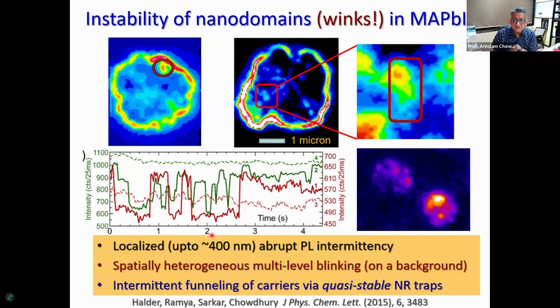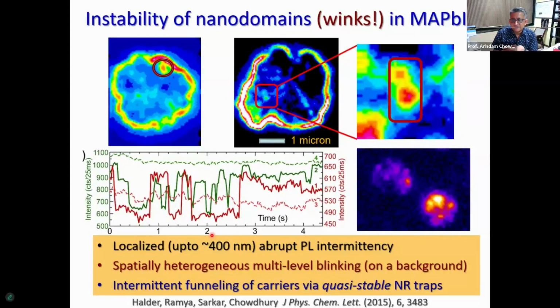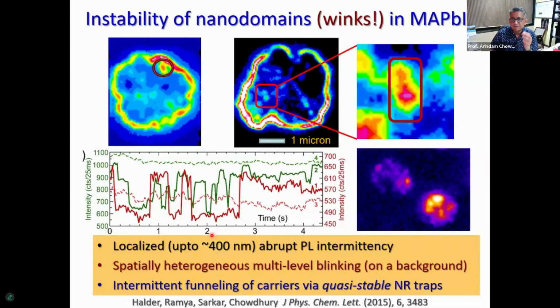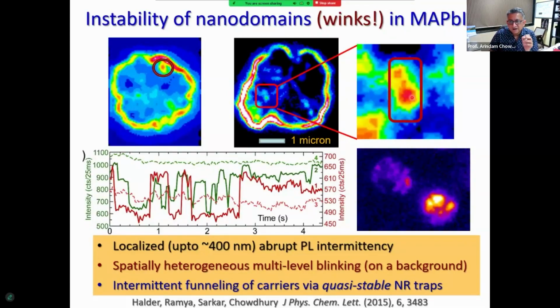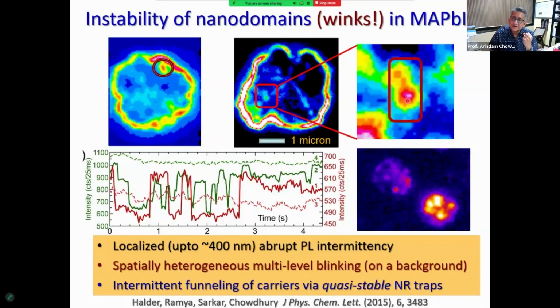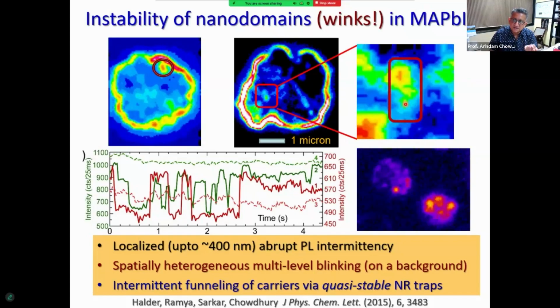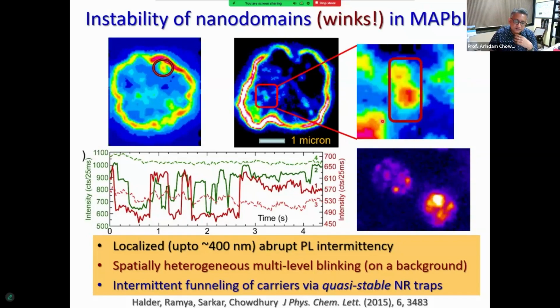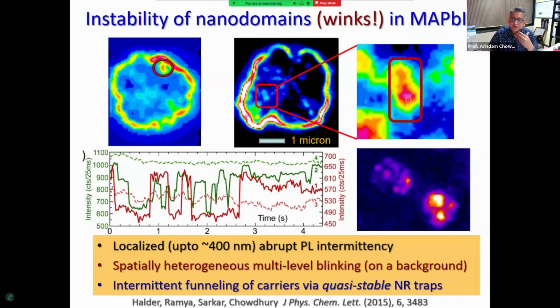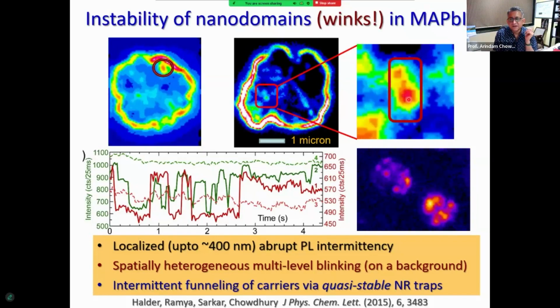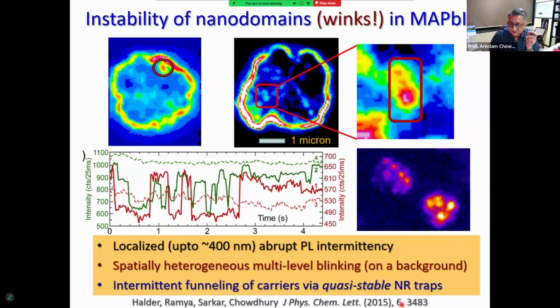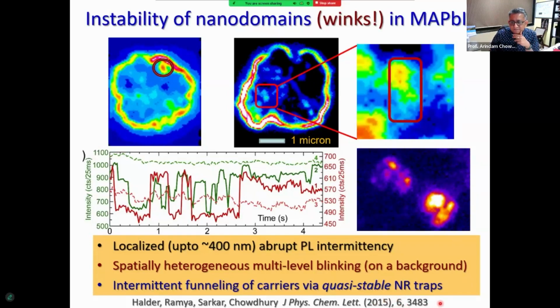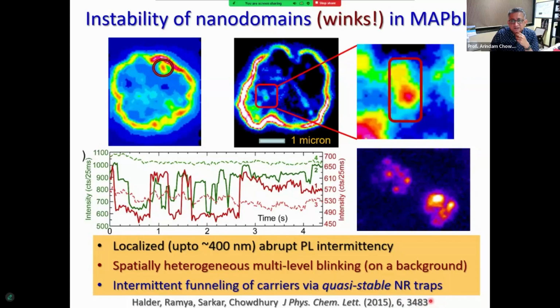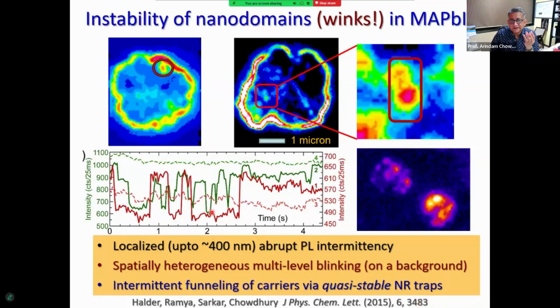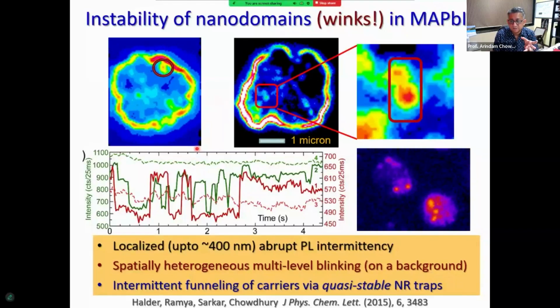So we attributed these to the funneling of carriers through some sort of defects that are formed locally in a local nanodomain, which is formed and it quenches the emission or quenches the carriers. And then somehow there's a saturation of these defects that leads to the emission being started back on. I believe this was one of the first papers in the literature where we showed that in a bulk material, there can be local domains which can undergo blinking. That was in Journal of Physical Chemistry Letters.